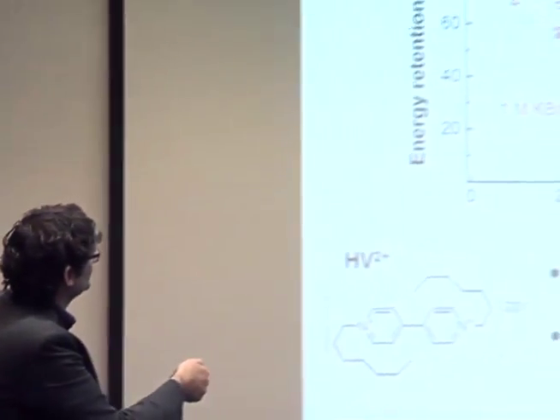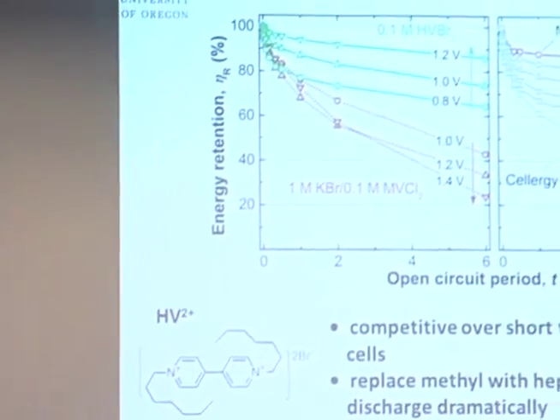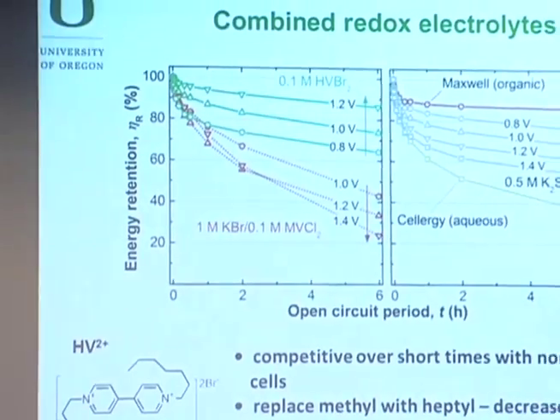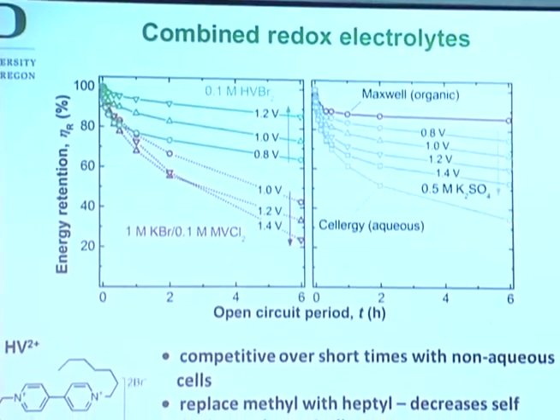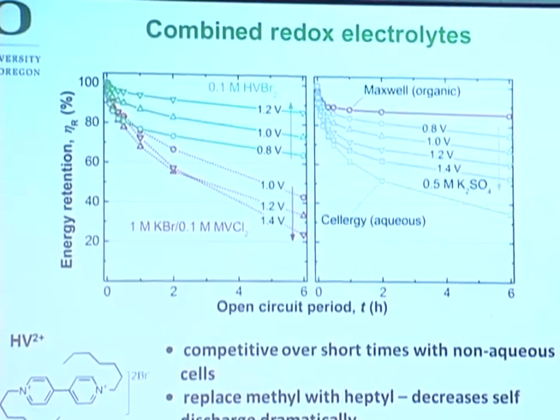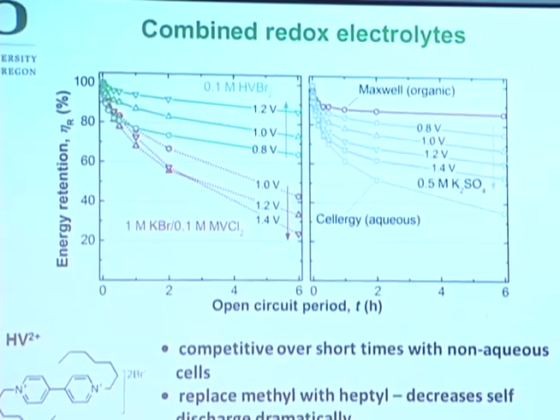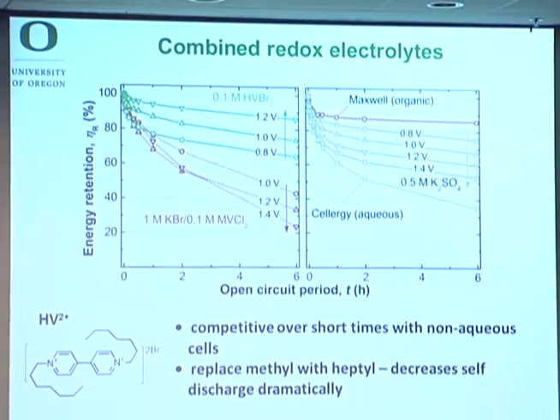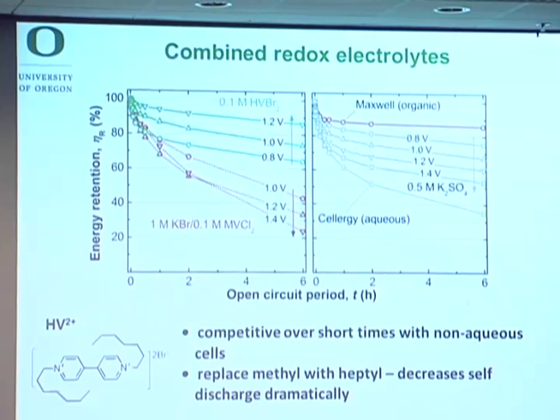You look at the self-discharge data, and for the methyl-viologen bromide system, while its self-discharge is a little bit worse than the control capacitor, it's still pretty good at short times, and not worse at all than a commercial aqueous capacitor that we got from Cellergy. It's not nearly as good as the organic cells from Maxwell.